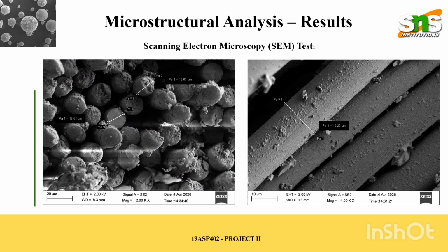Microstructural analysis is carried out using scanning electron microscopy. This technique helps in observing the surface morphology, fiber alignment, and bonding between the fiber and matrix. The images reveal good adhesion between the glass and jute fibers with the epoxy matrix, which plays a key role in effective load transfer and overall strength of the composite.